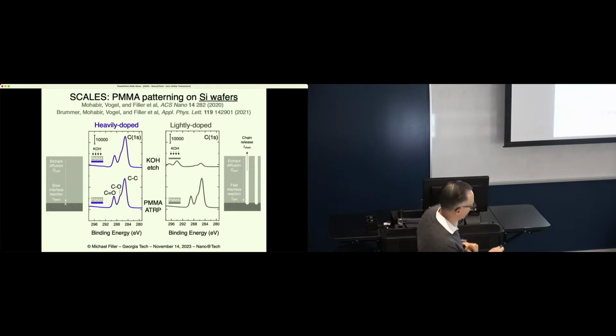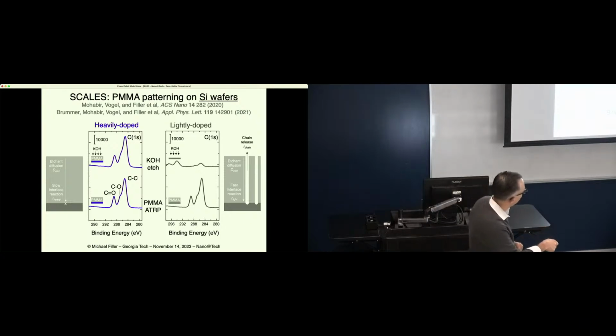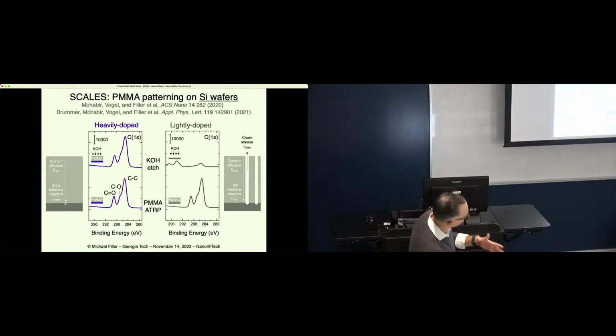And again, just to remind you of what's going on here, on the heavily doped wafer, the etchant is diffusing through but can't attack the underlying silicon to which the polymer is attached. On this side, it can diffuse through and start to break the connection of the silicon to the rest of the chain, and in doing so, we start to remove chains into solution.